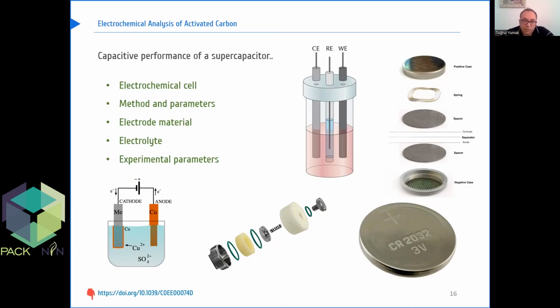The electrolyte is also very important, and common aqueous electrolytes include 6 molar potassium hydroxide and 1 molar sulfuric acid. Since energy stored is related to the square of the voltage, organic electrolytes are currently used in commercial capacitors due to the wider electrochemical working voltage window, about 2.7 volts compared to about 1 volt for aqueous electrolytes.